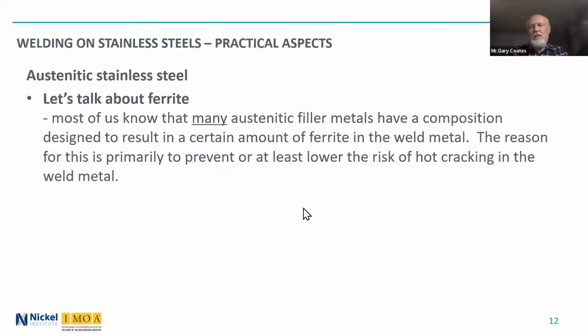So there's lots of things I can talk about in austenitic stainless steel. I'm going to focus mostly on the ferrite content. Most of us know that many, not all, of the austenitic filler metals have a composition designed to result in a certain amount of ferrite in the weld metal. And the reason for this is to prevent or at least lower the risk of hot cracking in the weld metal.